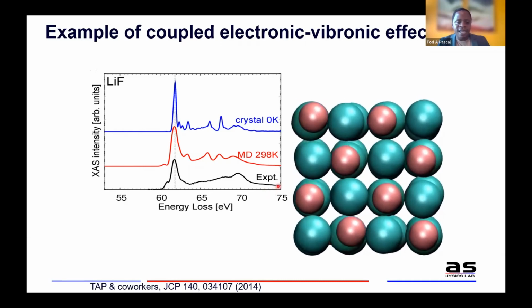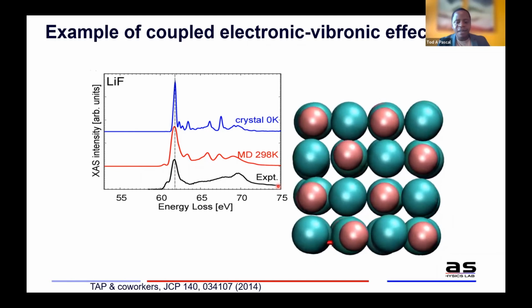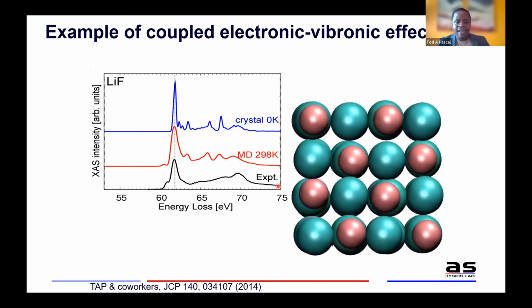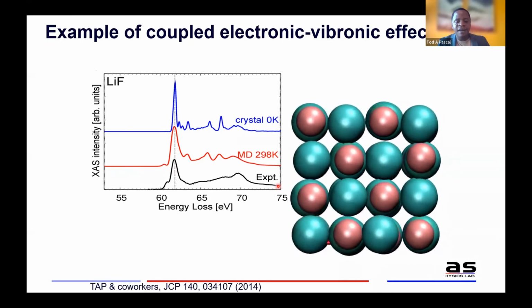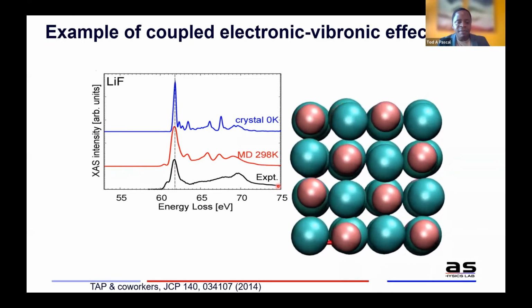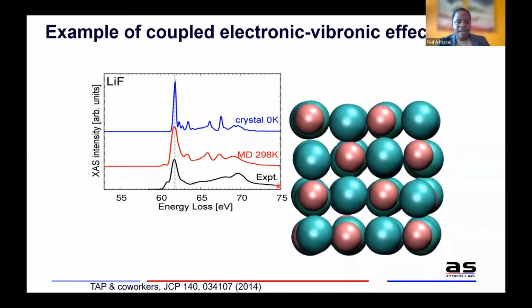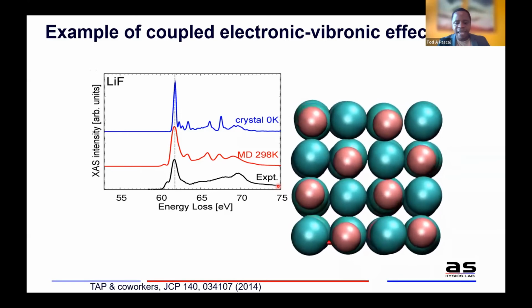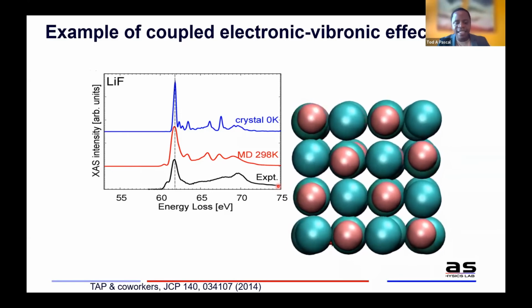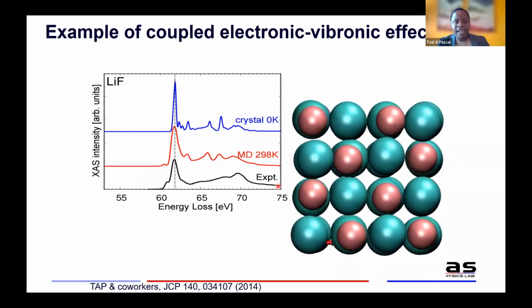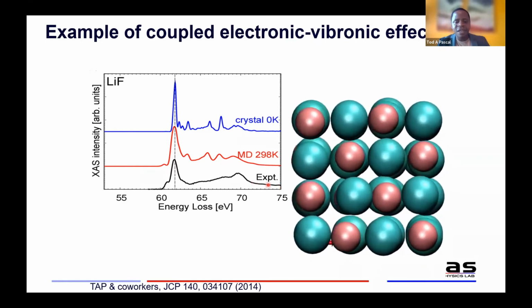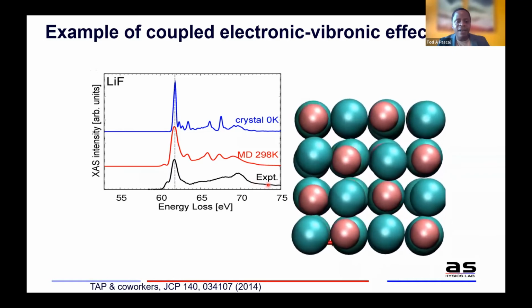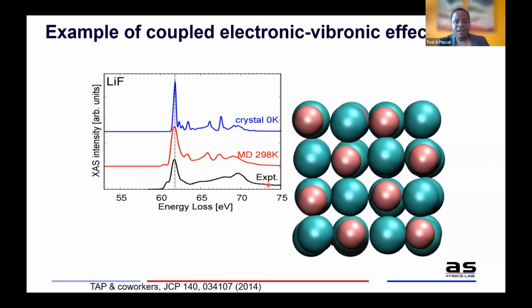And so for a long time now, there's been a push to try to understand the composition of these solid electrolyte interfaces and to maybe try to engineer new ones that will be more effective and more mechanically stable. And so it turns out that XAS is a very good probe at looking at these sort of compounds, because we get distinct spectral shifts depending on the coordination environment around the lithium.